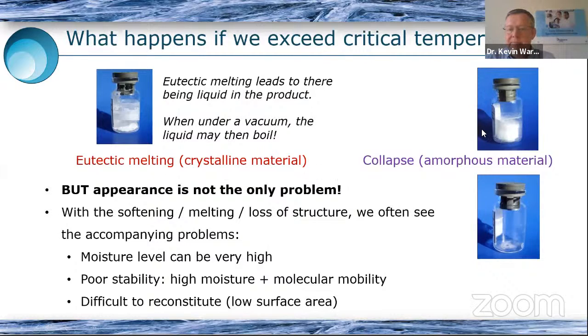Over on the right here, these are examples of amorphous materials. The top one is a sample which has just started to lose its structure. Perhaps not significantly, but the indication that it started to lose its structure comes from the fact that it's a very uneven shape. It's no longer uniform, it's not cylindrical, the top isn't even horizontal. So this is an indication that we've just started to see softening and loss of the structure in this particular example. So if we saw this, then the next time we freeze dry this material, we'd probably know that we'd been close to its collapse temperature, and so we might just need to use slightly less energetic conditions next time.